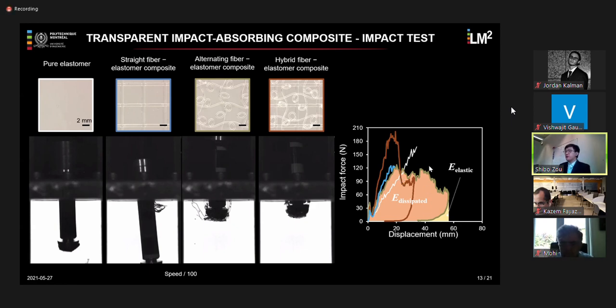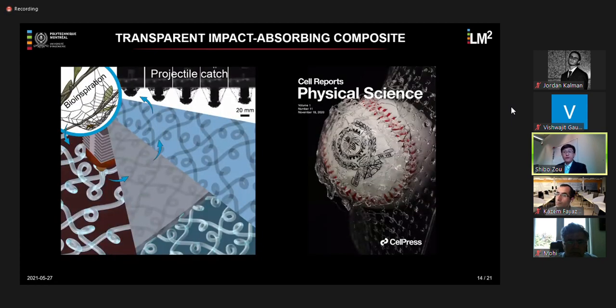This way we were able to calculate the hysteresis, which is the ratio of the dissipated energy over the total amount of energy. And we found that during the impact, up to 95% of the total absorbed energy was actually dissipated out of the material. This proves that we are able to implement the sacrificial bonds toughening mechanism in engineering materials and achieve this high energy dissipation behavior, which is similar to the spider web.